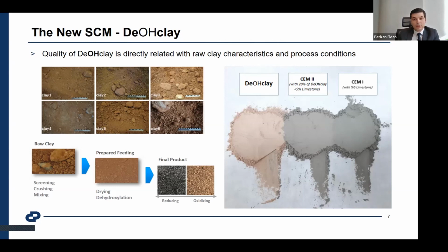At that point, color is a critical point with clay because it includes iron oxide content, and oxidization of iron oxide after 500 degrees creates a reddish color due to the formation of hematite. At that point, there should be a reducing atmosphere to control it. If the process is done in a reducing atmosphere, then its color becomes much darker. As you can see, two samples here, one in a completely reduced atmosphere, the other in the oxidized one. According to the amount of iron oxide content, it goes from pinkish to reddish colors.